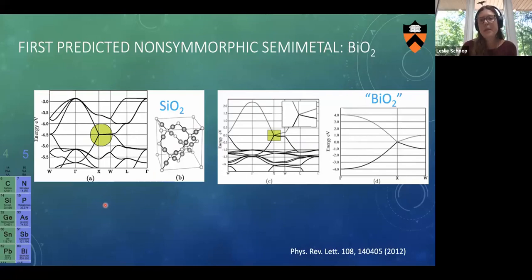But then the authors said, well, if instead of silicon I put a bismuth in this position, they're adding an electron. Here's our periodic table. Silicon is here, bismuth is there. With this, they get rid of the problem that this is below the Fermi level, so it moves up, and we get the Fermi level at this crossing point. In addition, they move down the periodic table to add spin orbit coupling and lift these bands, which are very close to each other right here, away from each other. And so there are lots of issues with this material prediction, sadly.